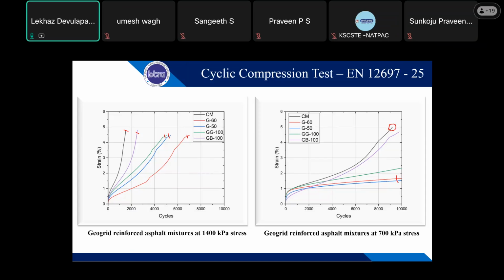This says that by placing a geogrid, we are going to improve our permanent strains. And one thing I need to mention, the failure criteria for this test was 4 to 5 percent strain. Suppose the strain has started at 0.1 percent for 1 cycle, our strain will increase as the cyclic loading increases. Whenever the strain has reached more than 4 or 4.5 percent, we consider that the sample has completely failed. This is our failure criteria for the cyclic compression test.